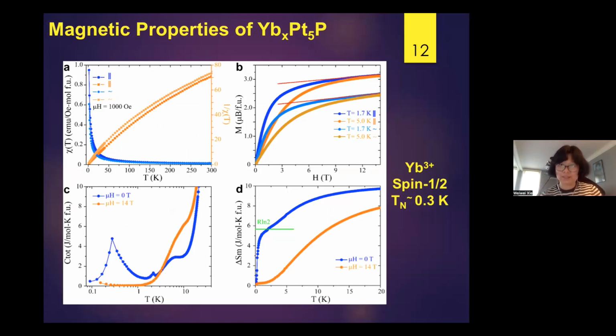what we got is that this is antiferromagnetic. And ytterbium shows 3+, and it's spin 1/2. And the transition temperature is very low. Okay, we measured down to 0.1 Kelvin. So the transition temperature is at 0.3 Kelvin.